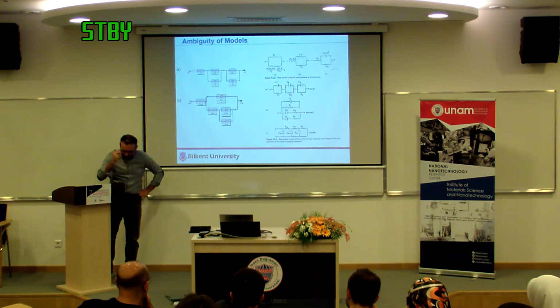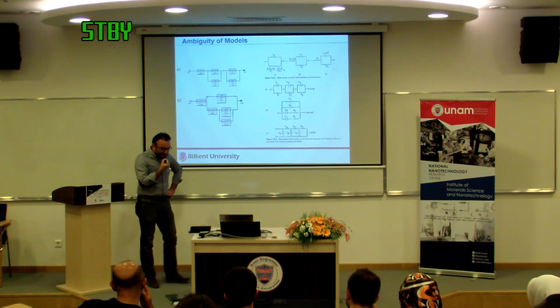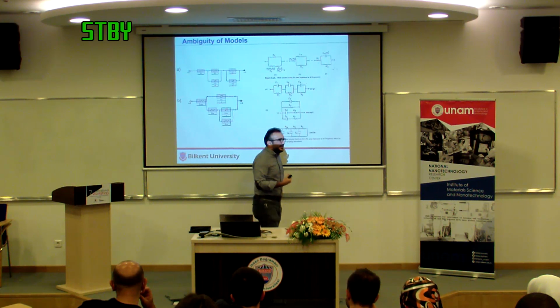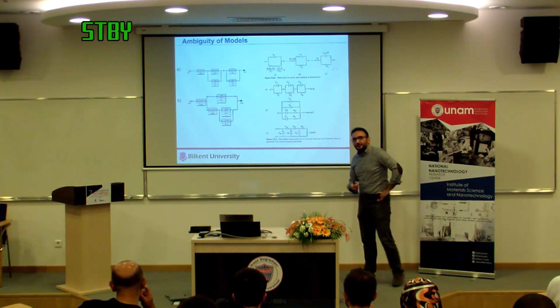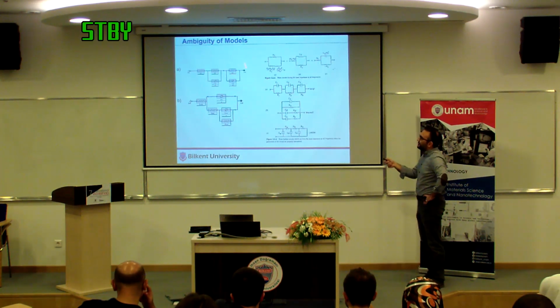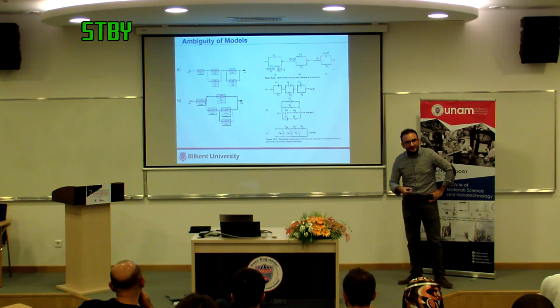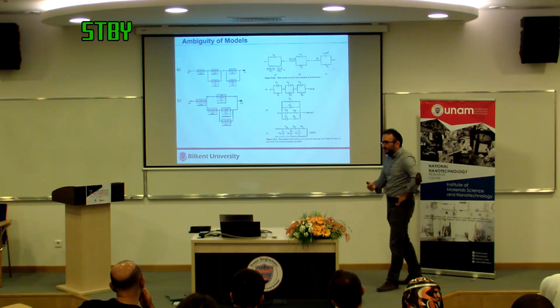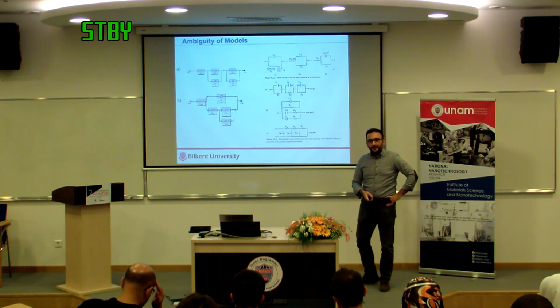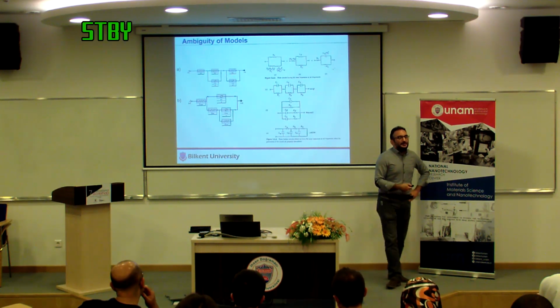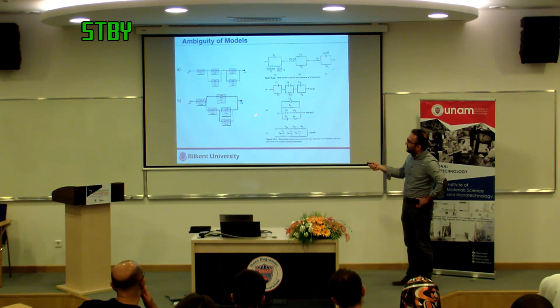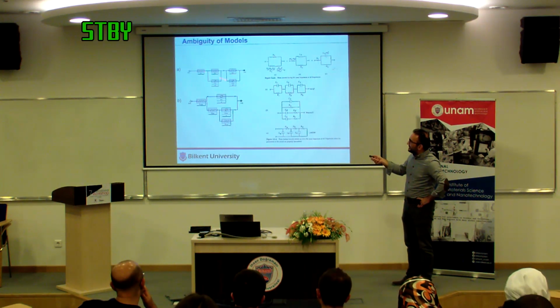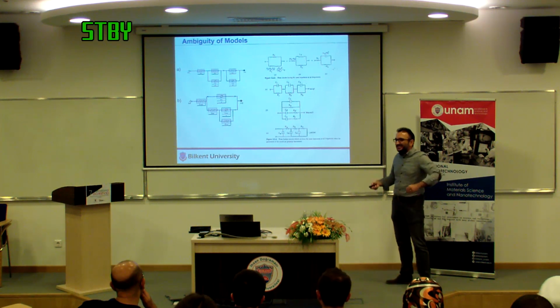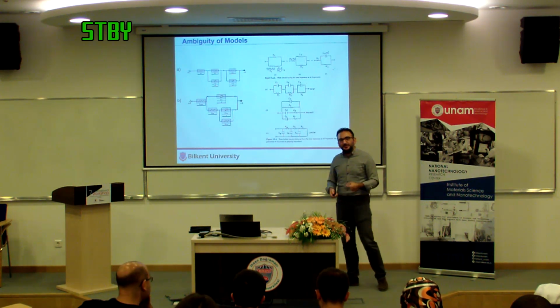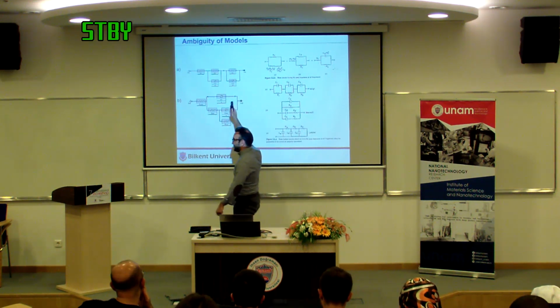Now the problem is, impedance spectroscopy by itself is not able to distinguish between certain circuit geometries. These two, for example, look like completely different circuits, and they are. But to the impedance spectroscopy measurement, to the EIS data, they are completely identical. There is an analytical equation that you can write from this to here. For different capacitor and resistor values, these two give you the exact same impedance spectrum. So just by impedance spectroscopy, you cannot distinguish between these two circuits.